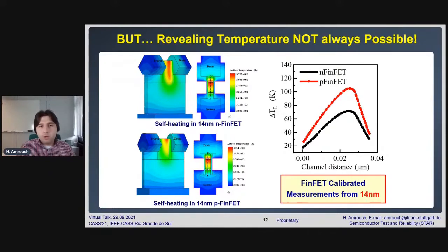It's like a room temperature, 27 degrees, like you see here in this analysis for 14 nanometer FinFET technology calibrated with industrial measurement data. We see how the temperature near the drain is so high, yet the substrate of the transistor, the silicon itself, is relatively cold. That die, again, if you measure the temperature of it, it will tell you it's still cold, but the transistor channel itself goes 100 degrees above the ambient temperature.